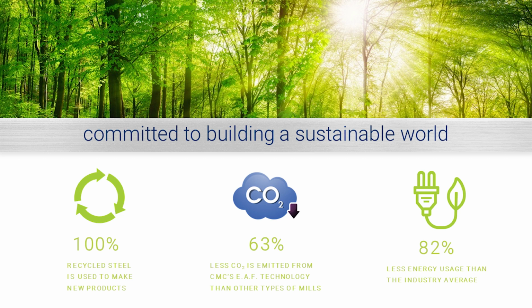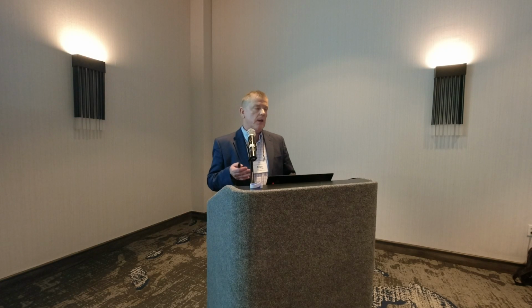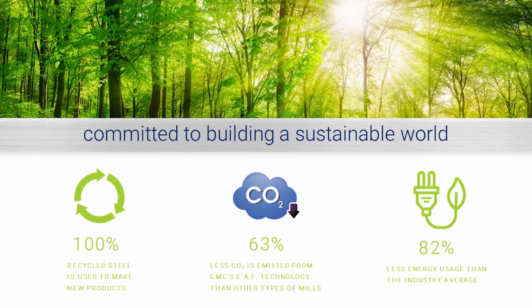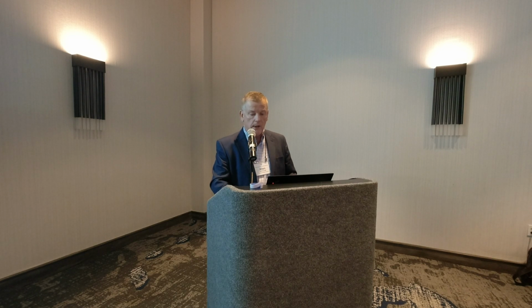The key thing, I mentioned that CMC has 100% recycled technologies, but they apply a scrap-based electric arc furnace steel making process, and so that's what really makes it possible to make these new products out of 100% recycled steel. There's a mill in Seguin that creates 100% recycled materials for the rebar, and this is going to reduce the CO2 emissions by up to 63% compared to what other mill operations are averaging around the country. And this is not only going to reduce that, but it's also going to help with the average energy use by 82%. And that's very, very important to point out towards preserving our natural resources.